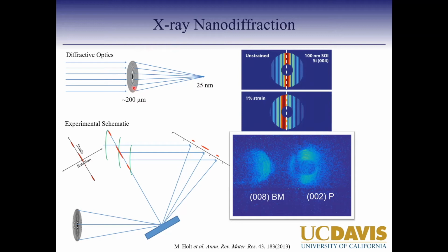So instead of looking like how we usually see a Bragg peak, a very nice Gaussian, your Bragg peak would actually look like this. This is purely because you have an imaging optics in the X-ray beam, which looks like that. Imagine your zone plate and Bragg peak on top of each other. Let's say this is where my Bragg peak is, this red. As it moves around, like here, I can estimate how much strain is in the sample as the Bragg peak moves around while I'm scanning. As you scan across 25 nanometers, you can track how the Bragg peak is moving, and you can calculate the strain in your material.